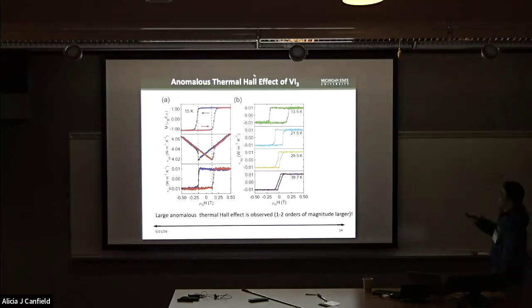Okay, so this slide shows the thermal Hall measurements, particularly focused on the figure on the right. You can see a very large thermal Hall signal over a wide range of temperature. They have two main features. One is the magnitude of the thermal Hall signal, which in this case is about 10 to the minus 2 watt per Kelvin per meter, almost one to two orders larger than the data I showed you earlier in the introduction.